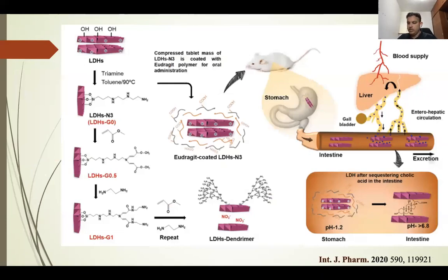So by using the same material, we have used this for intestinal cholic acid absorption. As I said just now, these positively charged layers could be used to load the negatively charged species. So for that reason, we have conjugated the diamine as well as triamine, and we make a dendrimer, so as to increase the hydrophobicity of the material and also pull the layer space, so that the cholic acid, which is sequestered inside the intestine, can be taken up, where you can see the mechanism over here. The Eudragit coated material as well as the dendrimer, which were entered into the stomach, because we coated here Eudragit.